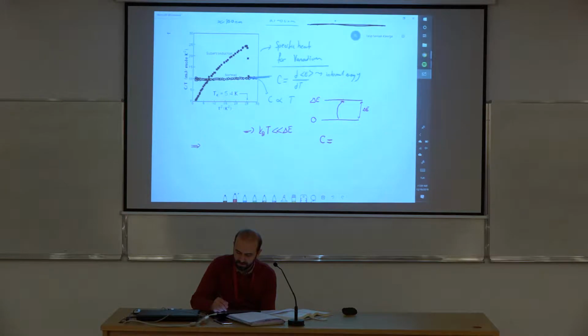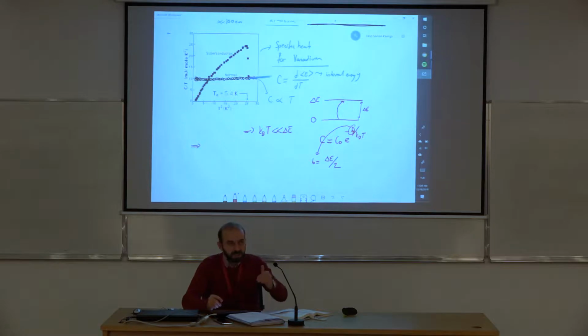So you have the specific heat, some C0, and then B over kBT. And it turns out that this B is half of the gap. So it's delta E over 2. And this is a very common trend we see in quantum systems or even superconducting systems. Whenever you have an energy gap, the charge transfer from one state to another follows such a relation, which is called, yes, Arrhenius type of relation.